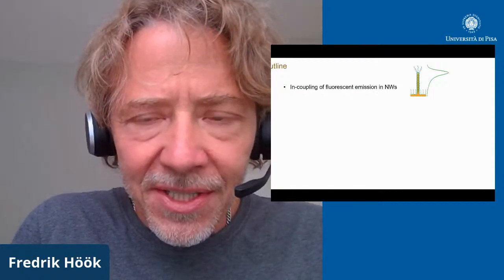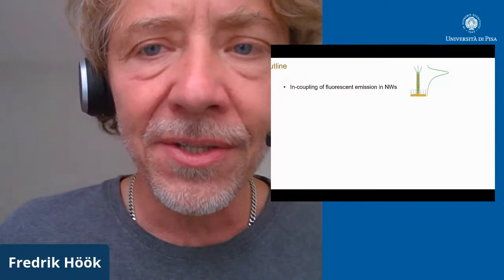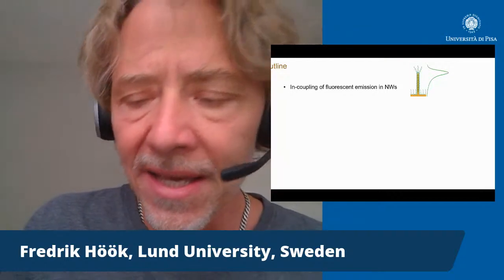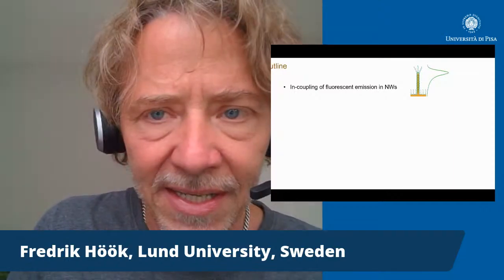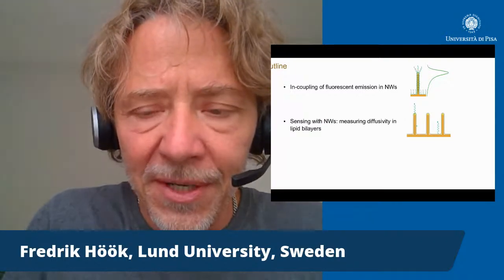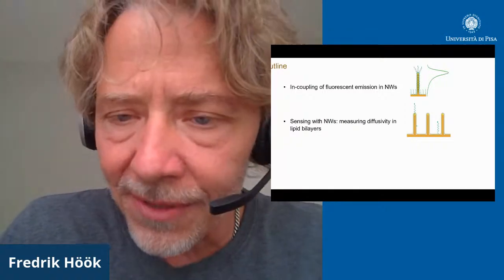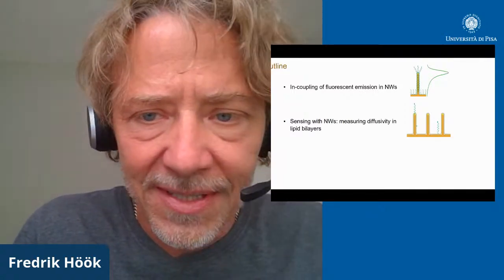And that relates to the nature by which, under certain conditions, certain fluorophores and certain properties of the nanowires, the light can be coupled into the nanowires, which act as light guides, emitting the light at the tip of the wire. And this actually leads to an enhancement of the fluorescence, which is highly interesting from a biosensor perspective, because this allows a convenient means to increase the signal while not increasing the noise, so that the signal to noise can increase quite dramatically, and that is what we have explored in the context of bioanalytical sensing.